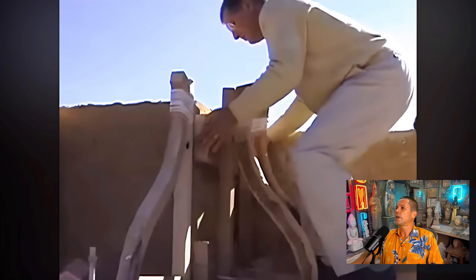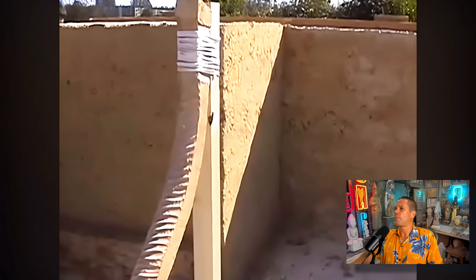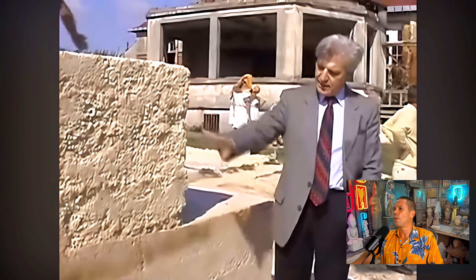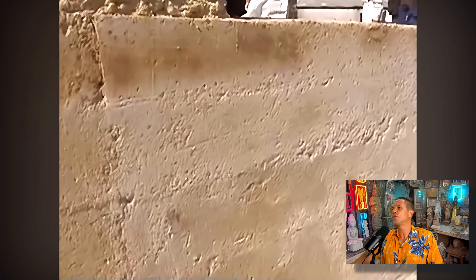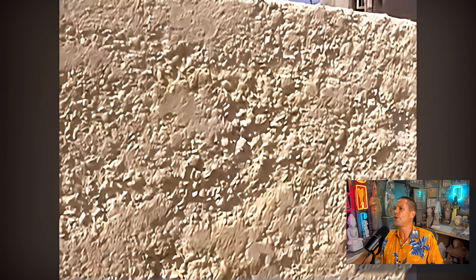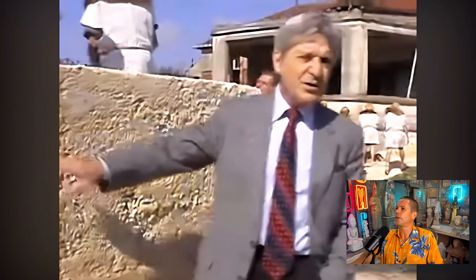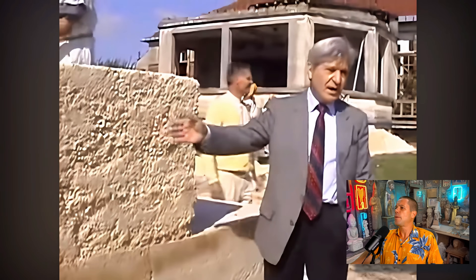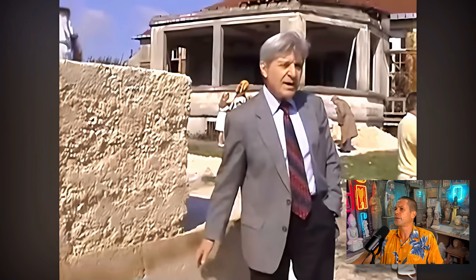The synthetic limestone looked like natural stone with no traces of visible wood grains. Four blocks had already been made. Joseph Davidovits presents them. The two large blocks, weighing up to four and a half tons, had the highest water content and the smoothest surfaces. The two smaller blocks, weighing around 1.3 tons, contained less moisture and had rougher textures. Davidovits said: when you look at the stones of the pyramid, you see either smooth blocks or very crude blocks — and they were able to replicate these textures just by varying the amount of water, which depends also on the climate and the weather.